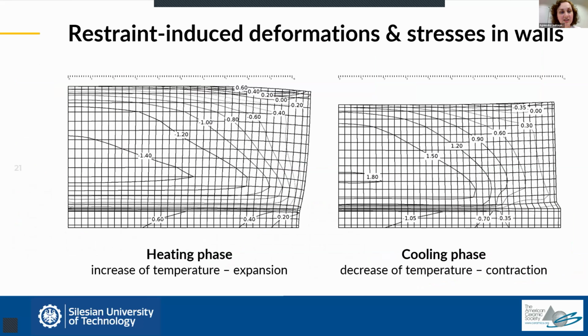We have a heating phase, increase of temperature, which results in the increase in volume, especially increase in length, which means the wall tries to elongate. And in the cooling phase, when the temperature decreases, the wall starts to shorten, or it would like to shorten. But since it is restrained, this deformation is partially limited. That is why the stresses occur in the wall.